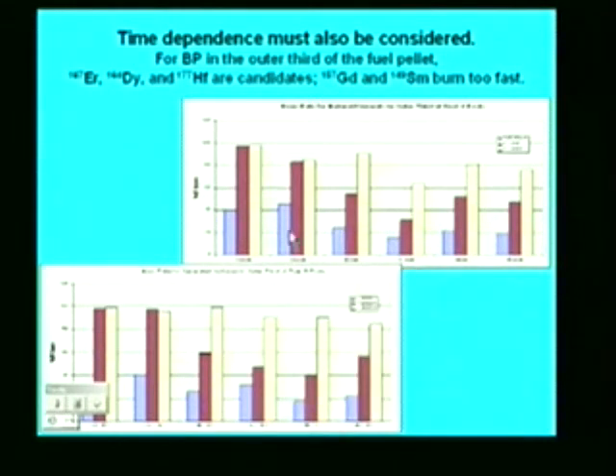We have the case of putting the burnable poison in the outer third of the fuel pellet. And if we look at these two curves, first two graphs, the first one is for the natural elements, the second one is for separated isotopes. The first thing we notice is that for the case of the separated isotopes, we in general burn them more completely. Well, we already knew that. If we look at the case of gadolinium on either natural or isotope, it looks like we're burning it far too fast because after just 1 year, essentially all our burnable poison's gone. Same thing with samarium-149. But if we go to erbium-167, we find a much more uniform burnup. And the same is true for the erbium isotope as well.